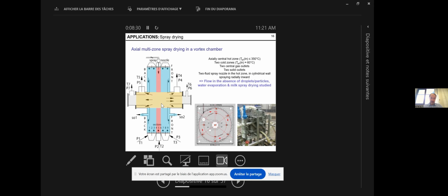The objective here from our collaborators was to reduce the size of spray dryers and, if possible, improve the energy efficiency. And we tried different concepts. We started from where we were working in coating and tried axial multi-zone operation. From the beginning, we had in mind to work with drying in two steps. A fast initial drying with hot air and then a final drying with more mild temperature air. The reason for that is that you have to very fast form an initial particle, an initial crust as we call it,